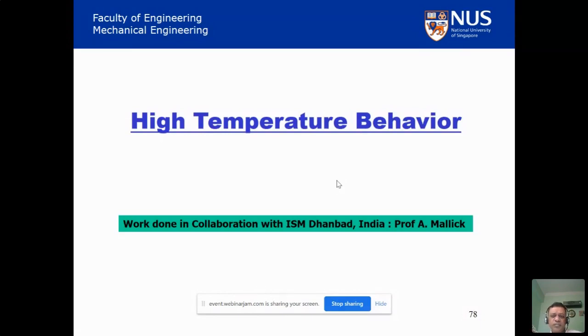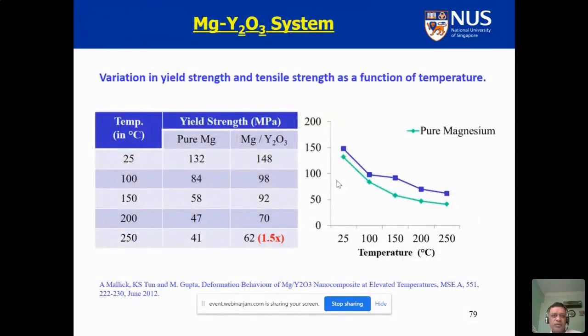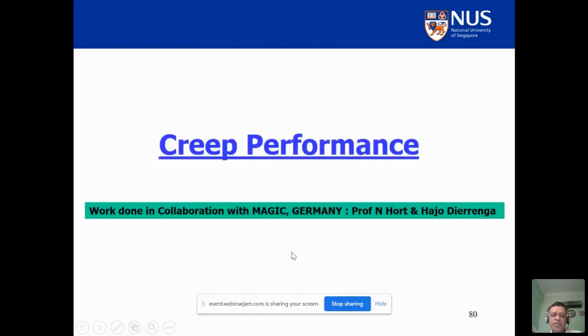Also, this work we did with Professor Ashish Malik in IIT Dhanbad. He was our former student at the National University of Singapore. In this case, he investigated the magnesium yttria (Mg/Y2O3) system up to a temperature of 250, which is beyond what we wanted to test, but we found that for every temperature, the performance of the composite, shown by the blue curve here, is superior to the unreinforced material, which is almost 1.5 times at 250 degrees centigrade, as shown in the table.